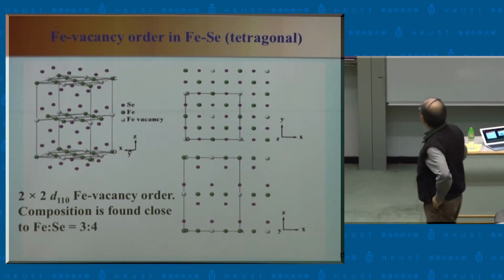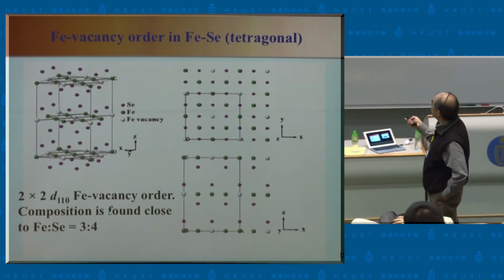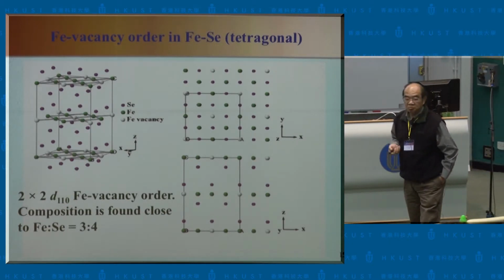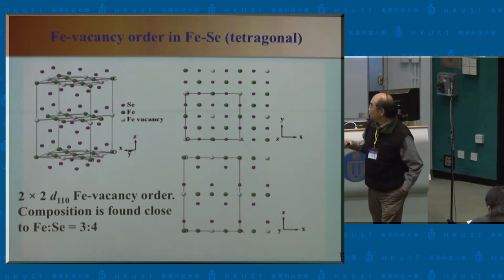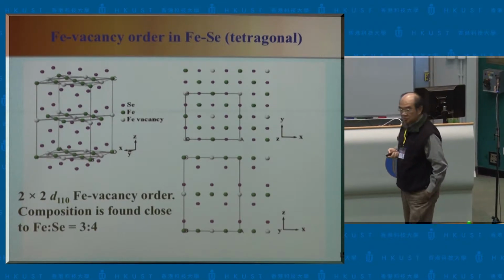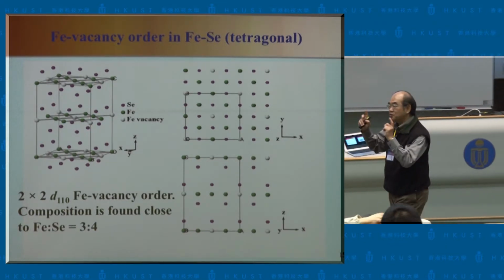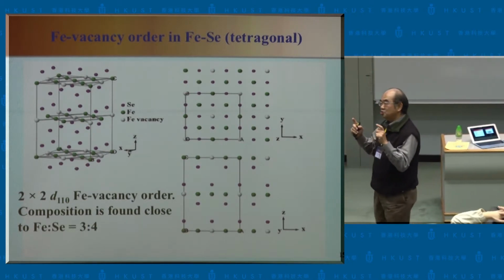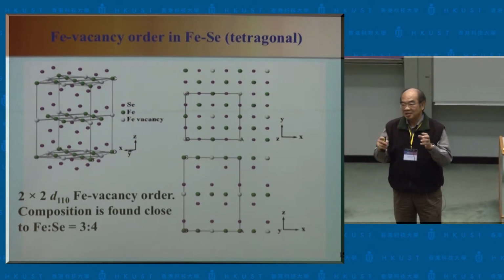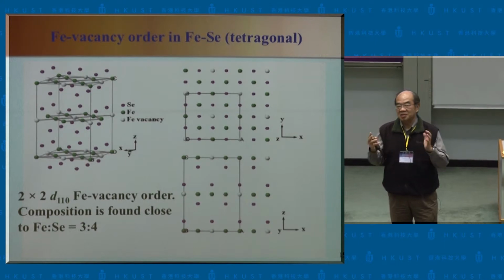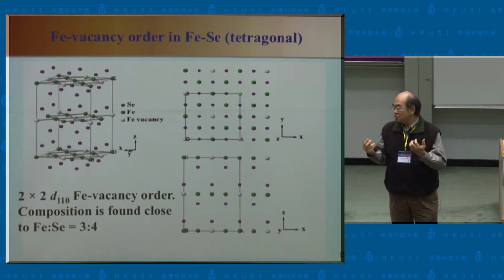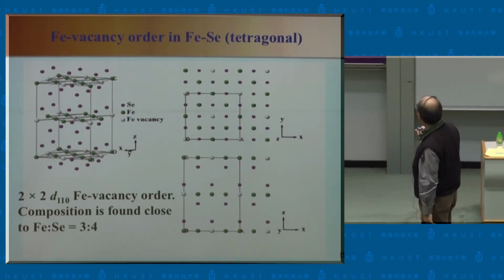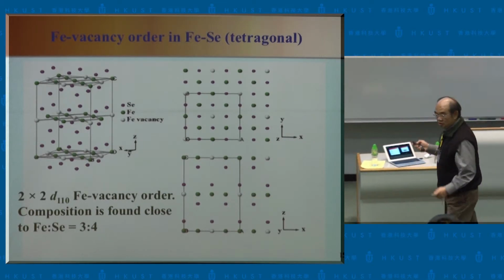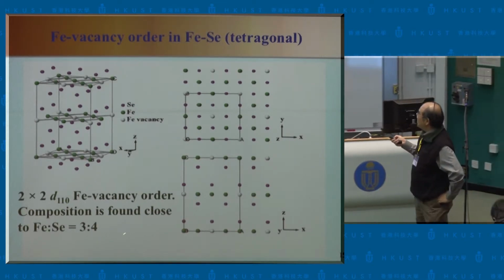Okay. And composition-wise, this system clearly shows that the iron to selenium ratio is 3 to 4. So in fact, we do have this tetragonal 3-to-4 phase. Usually, in the material science phase diagram of iron selenide, you only show the hexagonal phase. But now, under certain conditions, you can stabilize this tetragonal 3-to-4 phase, which is non-superconducting and with some magnetic feature.